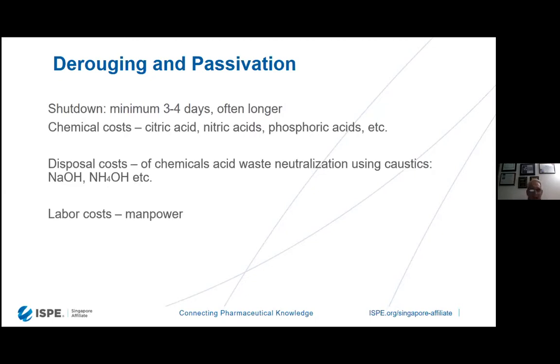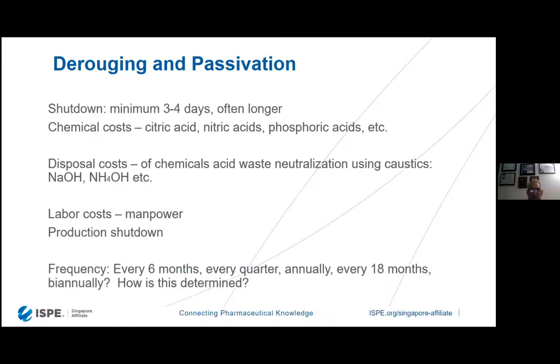In Singapore, as an example, where water is recycled through NEWater, bringing up the pH is extremely important because there are only certain levels of pH that can be dealt with in NEWater. The water that goes back for recycling needs to have a pH close to 7. So using sodium hydroxide or ammonium hydroxide is how that happens. So you have chemical costs associated with the neutralization, you have labor costs and manpower, production shutdown, and every 3 to 6 months, or quarterly, or annually, or 18 months, some people will do the frequency. How is this determined? Well, it's not determined scientifically if you're doing it by discoloration or some SOP that was devised a decade or 2 decades ago by someone who probably no longer works in your company.